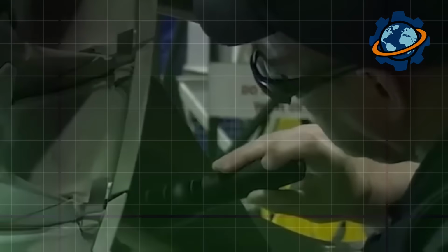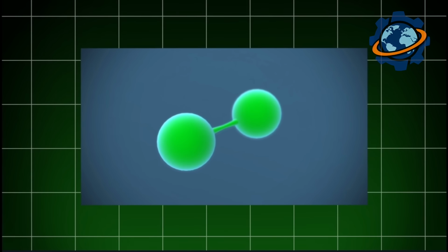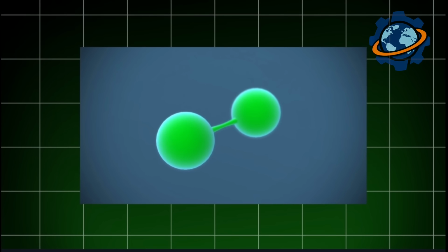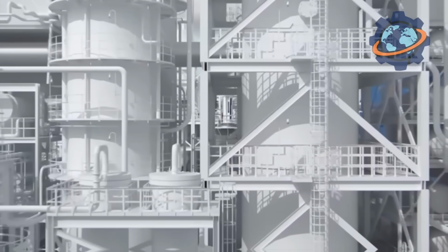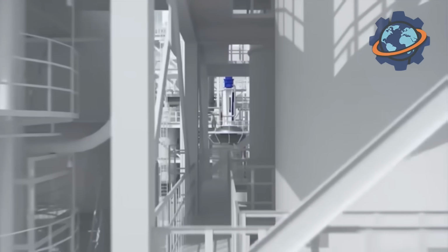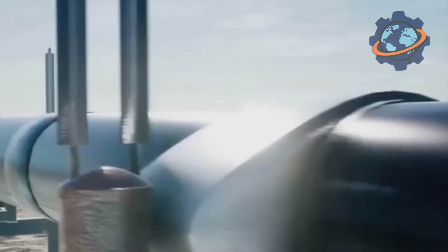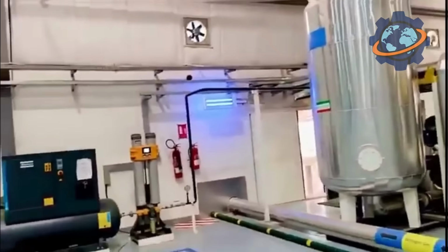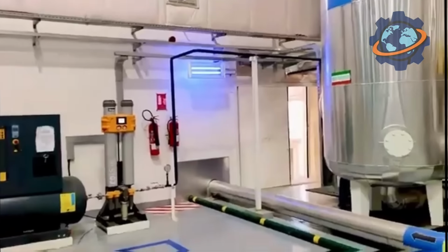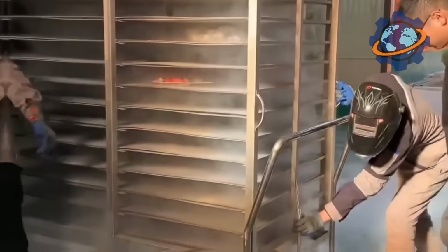Then comes the thermal barrier coating, yttria-stabilized zirconia ceramic, applied atom layer by atom layer using electron beam physical vapor deposition. In vacuum chambers, electron beams vaporize ceramic ingots. The vapor condenses on rotating blades, building up a coating 0.08 of an inch thick with a columnar microstructure full of microscopic pores.